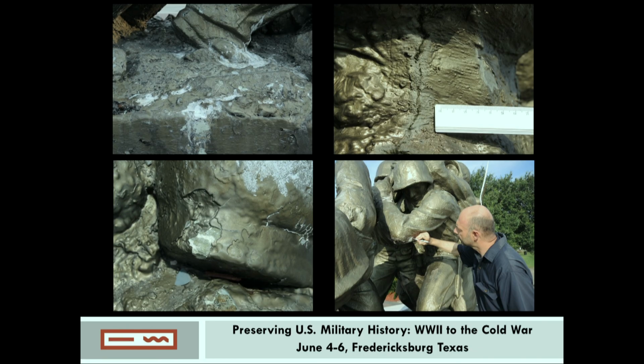You can see a little bit on this slide. It was not possible to do justice to what we could see, but I included a few close-ups just to show the number of coatings we could see. There ended up being 11, but I'll show you that when we do the coating removal section. There was clay coming out, it's staining the surface. We had salts, we had pretty much every problem.